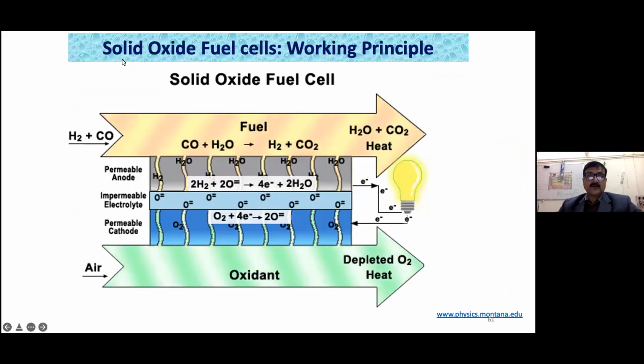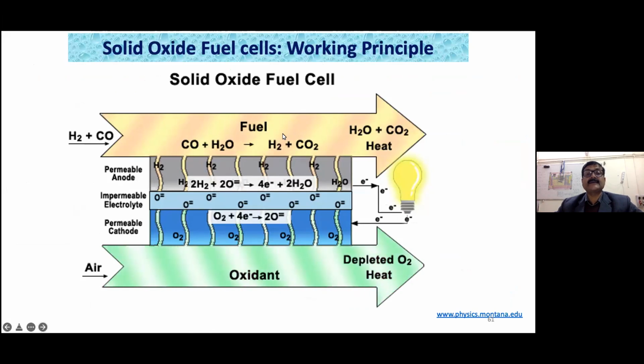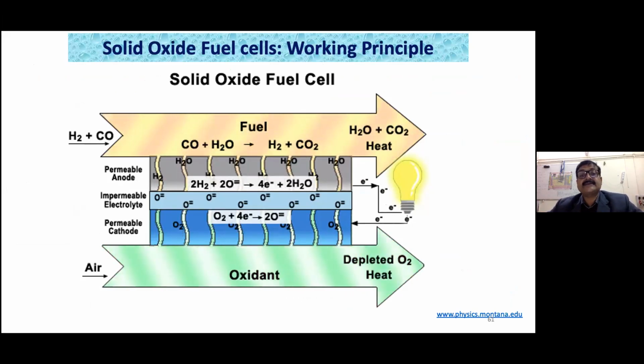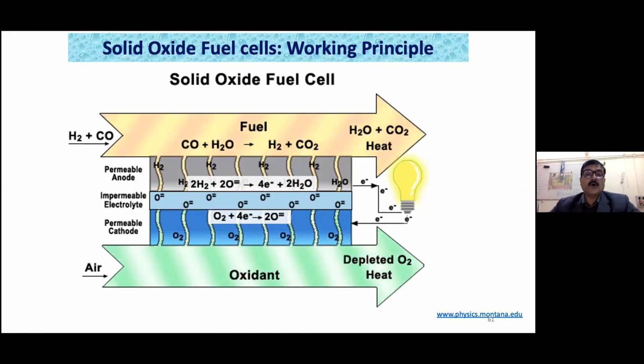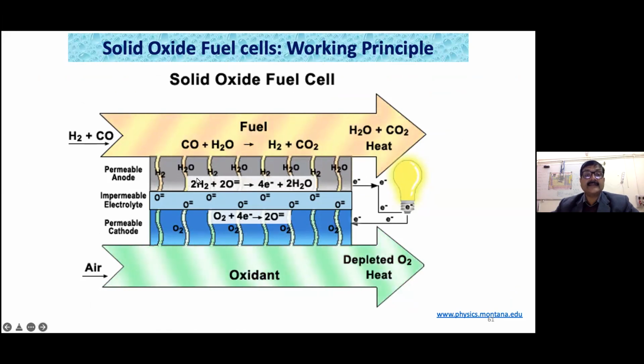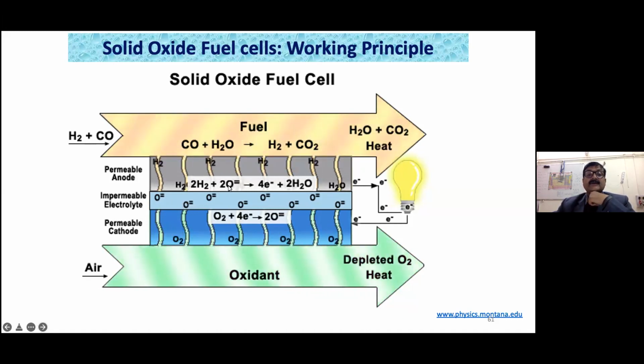So you see that I'm talking of the solid oxide fuel cells because it has the highest efficiency, and the only drawback is it needs a very high temperature to get it operated. So you see that in this case, you need to have the hydrogen with the carbon monoxide as a fuel, and at the anode, this hydrogen is interacting with the oxygen ion which is coming from the cathode through this electrolyte material, and when it is reacting, this leaves 4 electrons and water, simple pure water.